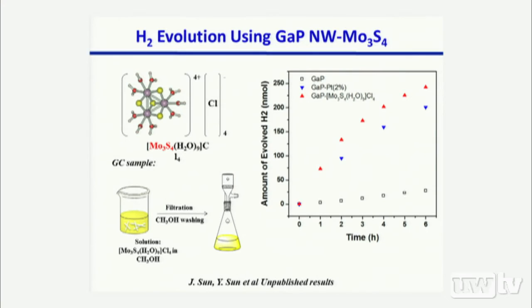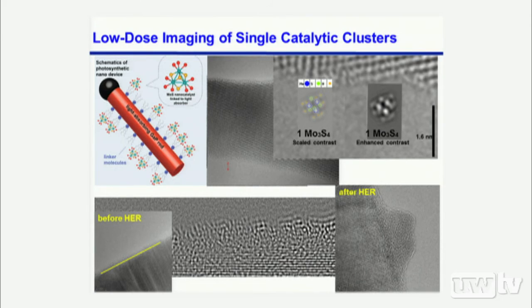In this case, we're interfacing gallium phosphide nanowire with one fairly powerful water reduction catalyst, the molybdenum sulfide cubane molecule. In terms of activity, you can see that it's comparable to a 2% loaded Pt sample. So molybdenum sulfide can eventually be used as a very efficient water reduction catalyst. And these are more details about these molybdenum sulfide catalysts.